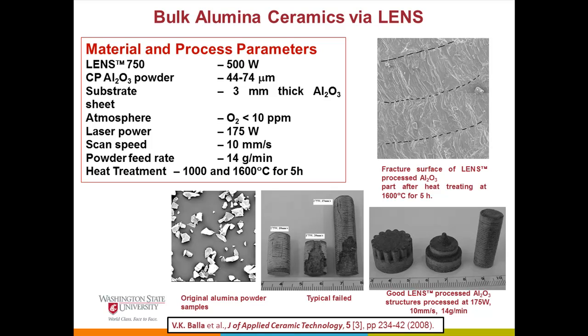Word of caution, two things. Number one, because it's a ceramic, it has very poor thermal stress management. If we want to make a big structure with this approach, it may not work because of the poor thermal shock resistance of most ceramics, if not all - it will crack. So we're good with about 1 inch size parts; anything beyond that is a problem. If it's a layer coating, just pure ceramic coating, we're good there as well. So this technique works very well for small size ceramic parts.